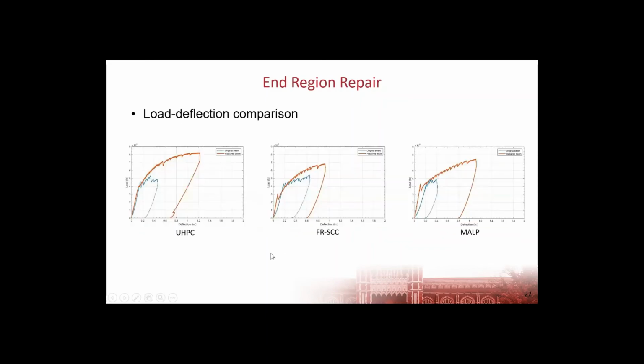If we look at a comparison of the pre-repair and post-repair load tests, which is shown here, we can see the blue lines for the pre-repair tests all are pretty indicative of bond shear type failures, where we have this bond loss that's causing us to have a more or less consistent load, but it's not a yielding type failure. It's a bond shear beam failure. Then we repair the specimens. In each case, we can see that we have an increased stiffness because, of course, we're adding cross-section to that repair. And in all cases, we had an increase in ultimate load and a shift to more of flexural behavior for the beams after we repaired them.